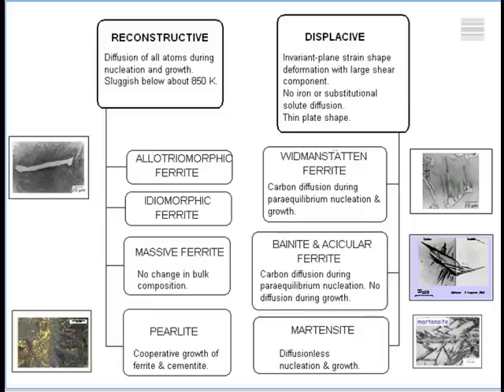You remember this slide where I categorized the different transformations into displacive and reconstructive. These are closer to equilibrium because diffusion occurs. Here, diffusion is not allowed. So you change the crystal structure by deforming the austenite into the structure of the ferrite. That deformation is real. If I take a crystal of austenite and polish it completely flat and then allow it to form martensite or bainite, you will see with your own eyes the deformation.